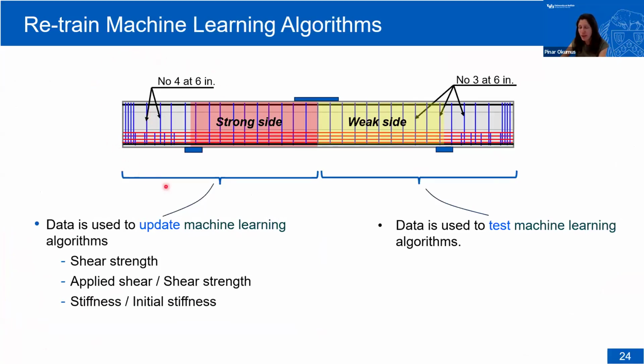So as you remember, we had data from both sides of the beam, so 2 sides, and we used them actually for 2 different purposes. The strong side data, we use it to update our machine learning algorithms. So any data we collect from there is going to be added to the database. And the data we get from the weak side, we never show that to the algorithm. So that's always unseen by the algorithm because we're using it to test the machine learning algorithms to assess the accuracy. So the two sides are similar, as I said, similar dimensions, but very different reinforcing ratios.